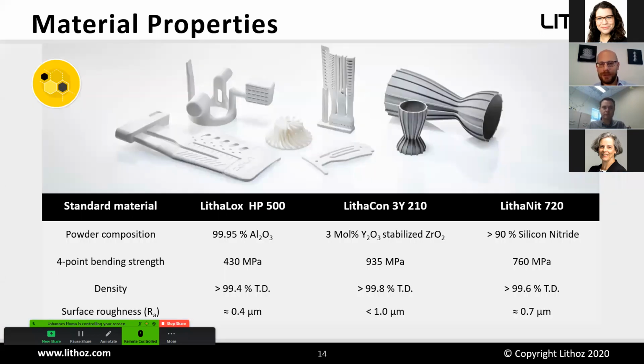And if you see here, for those, I guess most of the attendees are ceramic engineers who have ceramic knowledge. You can tell from these numbers that they are, compared to conventional forming, quite good in terms of bending strength. Density is, of course, very high, well above 99%, and the surface roughness is always very good as well, well below 1 micron. And as you see, all the parts which we are exhibiting in this presentation are not polished or ground. This is the as-printed quality.